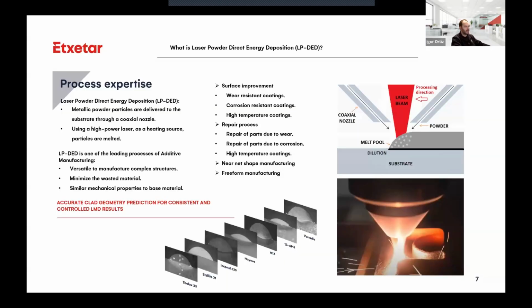So what is laser powder direct energy deposition? We use coaxial nozzles. They can be discrete nozzles, but we usually work with coaxial nozzles, which are two nozzles assembled together. Blown powder is injected through the nozzles, and a laser beam melts the powder in a substrate. During the process, there is a heat affected zone and a dilution, but compared to traditional welding, the heat affected zone is small. Also, we can control the track width and height in different materials with thermophysical powder material parameters.